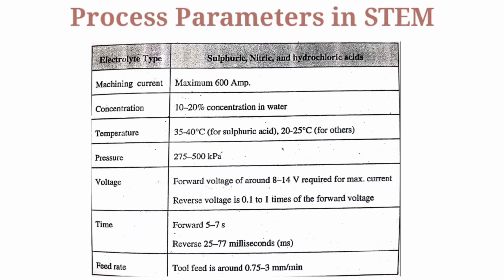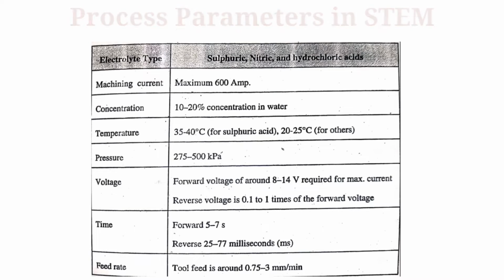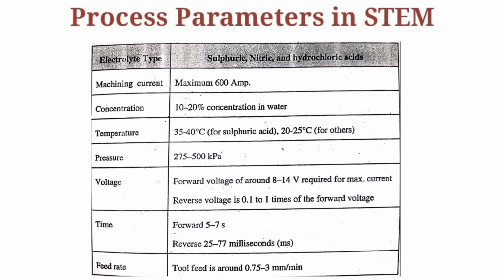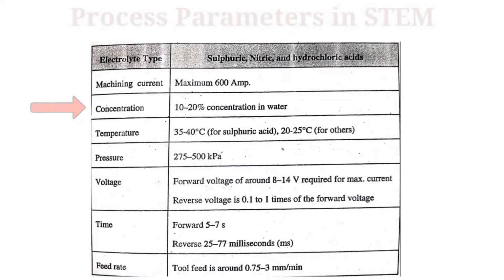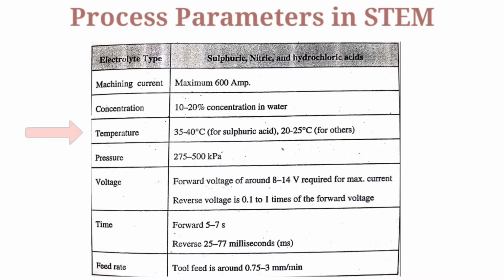The parameters which directly affect the quality of the process are: first one, the machining current. It should be maximum 600 ampere. Concentration should be 10 to 20% within the water. Next, temperature should be 35 to 40 degrees Celsius for sulfuric acid and 20 to 25 degrees Celsius for others. Pressure should be maintained at 275 to 500 kilopascal.